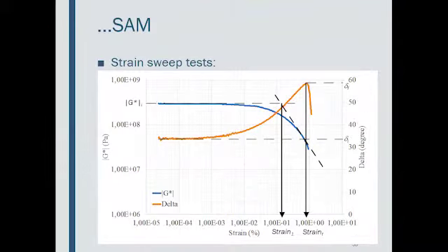And we are thinking about getting these 5 points for each curve: the initial complex modulus, the strain where you have the behavior changing in the curve, the initial phase angle, the phase angle at failure, and the strain at failure. So the plan is to check the variability of these parameters for each situation: temperature, geometry, and binder content, to figure out if we are having good repeatability with these tests.